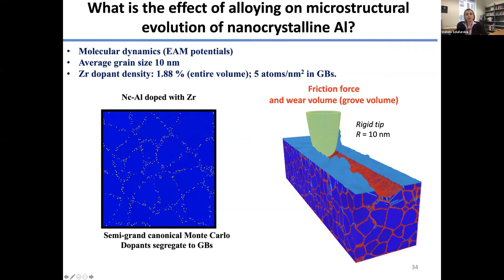So our samples have an average grain size of 10 nanometers in this case, and there are two reasons to do that in our simulations. First is that we wanted to study a large ensemble of grains in molecular dynamics simulations.